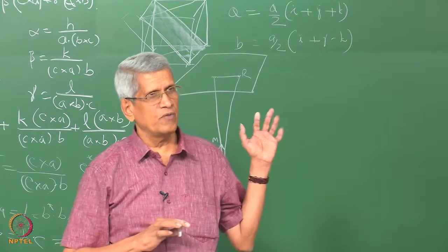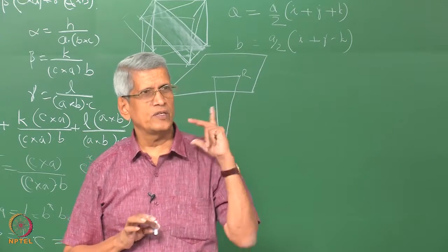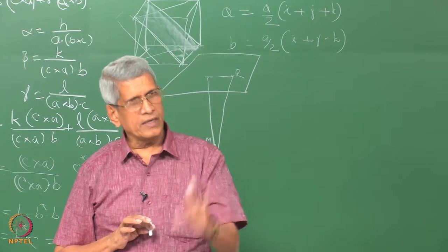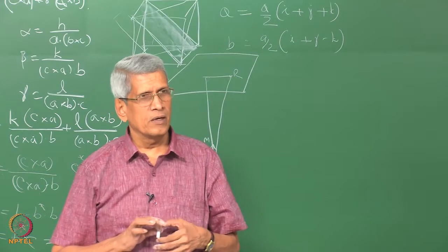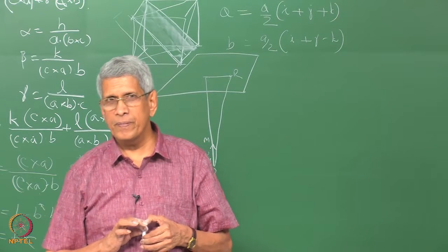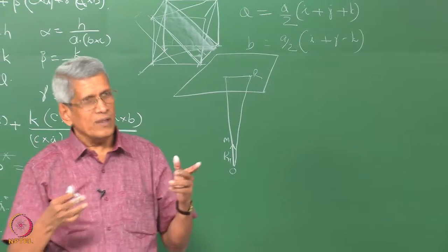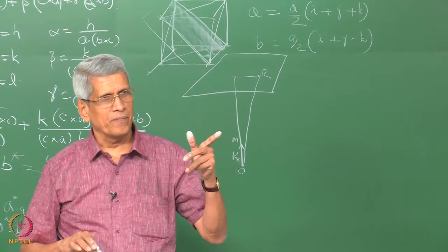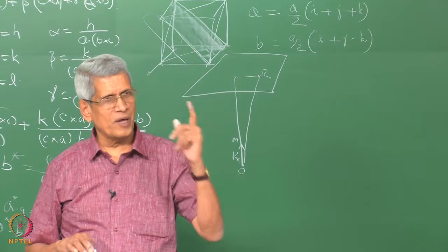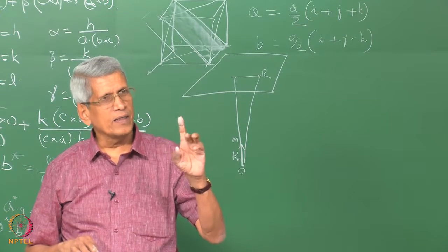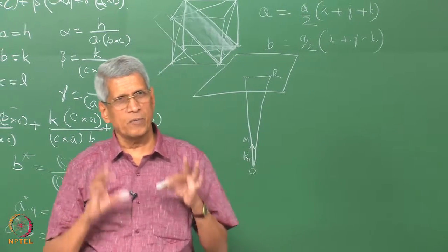When you create a unit cell in reciprocal space, a BCC unit cell looks like FCC, and an FCC unit cell resembles BCC, correct. Simple cubic will look like simple cubic. But for others there will be some rotation also. That is why I would like you to do some assignments on non-cubic systems, then you will understand how to do the reciprocal lattice.